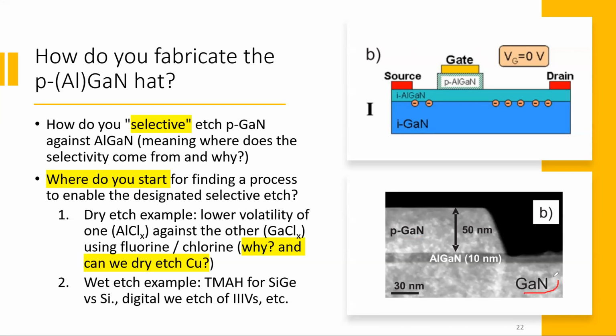And here, remember, you have the AlGaN here. If you put a p-GaN here, you can never form this. You can never form this one because if you have p-GaN on top of GaN, you can't etch stop. When you apply a gas, you can only time it to stop at some place. And here, if you put AlGaN here, you have a different element here. Then you can stop at these positions. This is called etch stop layer.